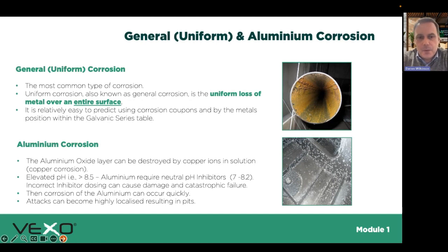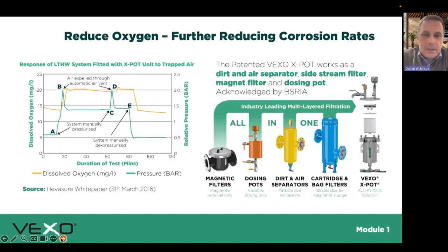So a huge amount of commercial boilers that are specified, and I know we are moving to heat pumps, and we should be moving to heat pumps or other technologies, certainly. But again, aluminium is a great metal in terms of ability to transfer heat most efficiently. Unfortunately, in a water treatment or water quality situation, aluminium is very sensitive to pH in particular. And a lot of common corrosion inhibitors used by water treatment companies are generally alkaline based. And aluminium requires neutral pH treatment. It needs to be maintained below 8.5. Anything over that, we're going to start seeing degradation of the actual aluminium. And you can see boiler failures typically as well, quite common.